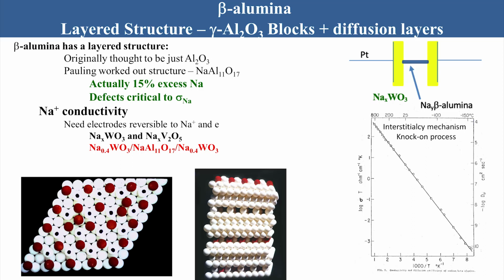And they move so fast you can't use what we call blocking electrodes like platinum. You had to have electrodes where the ions moved as well. So what we used were these sodium tungsten bronzes, sodium vanadium bronzes, same compounds I'd used for my doctorate. And those ions can move from, we didn't describe it as such in those days, but the cell I show you there is really a solid-state battery. You have your solid electrolyte, the beta alumina in the middle, and then you have your two solid electrodes, the tungsten bronze or the vanadium bronze. And we managed to measure the conductivity from liquid nitrogen temperature up to 800 degrees centigrade, and I think it's still the material with a single diffusion mechanism over the largest temperature range anybody knows.